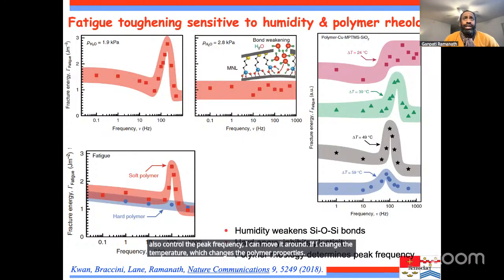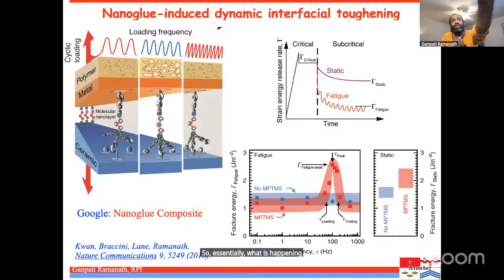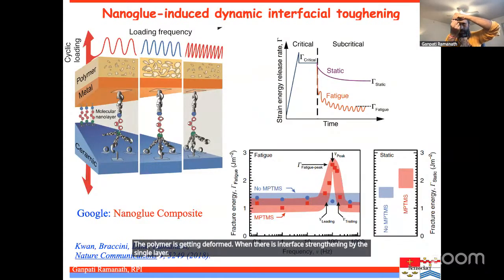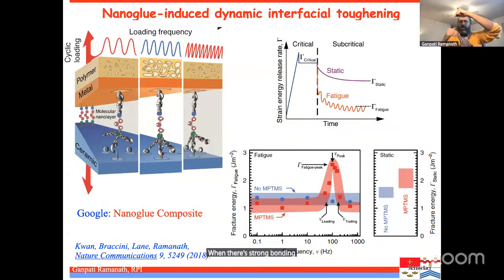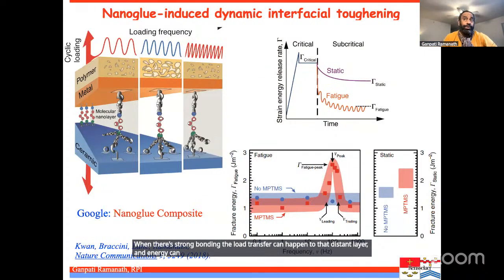So essentially what is happening, and that is shown in the top left graph here, the polymer is getting deformed when there is interface strengthening by the single layer. When there's strong bonding, the load transfer can happen to that distant layer and energy can get dissipated there, which will give you an increase in fracture energy.